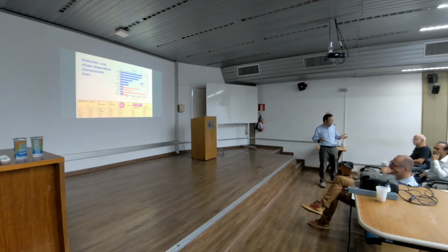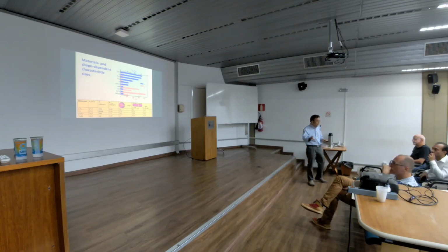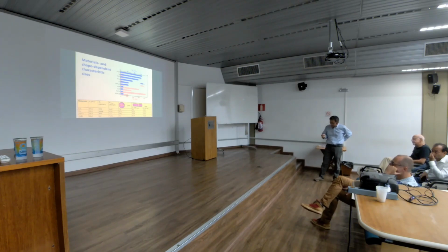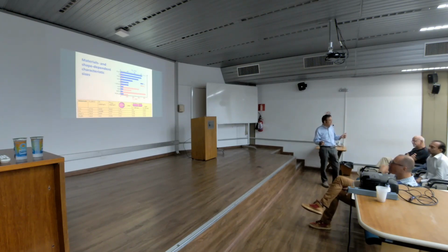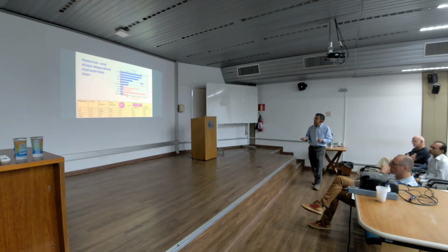However, another big issue came. We found that at the nanoscale the shape plays a huge role. It's also difficult to control the shape at the nanoscale. It's so small, we cannot see it. We have to use a microscope, like you guys are doing in the facility center. For example, if your shape changes from spherical to nanorods, this diameter can be much, much smaller than this diameter for the superparamagnetic transition. Is that important? Yeah, it's very important to know that.